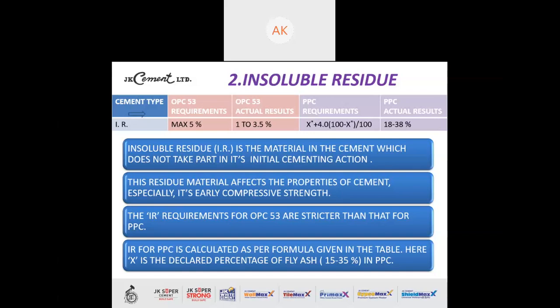Now the IR requirement for OPC 53 is stricter than that for PPC. If you see above, actual results for OPC are between 1 to 3.5, and for PPC are between 18 to 38%. So big difference. And fourth point, IR for PPC is calculated as per the formula given above. Here X is the declared percentage of fly ash, 15 to 35% in PPC. The IS code says that there should be minimum 15% and maximum 35% fly ash that can be added by the manufacturer to manufacture PPC cement. Next, please.